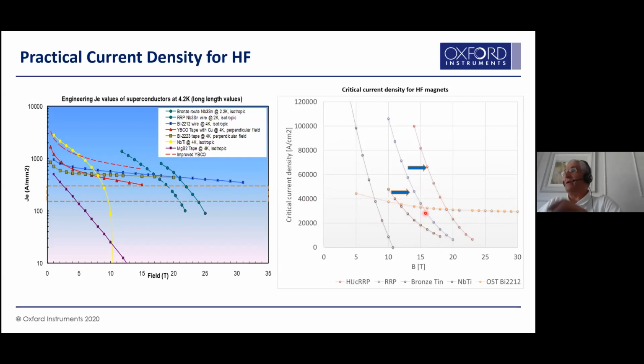And this has enabled a significant improvement in the performance of wire critical current density. And that's for a standard wire. You can see the significant improvement, almost 3-4 Tesla for the same current value. And then recently, OST has developed even higher JC performance, which means even higher current density for the same wire size. That has enabled us to start thinking about how to make these systems smaller in size, and we managed to reduce their size by almost 30-40%. However, this has come at a price of coil structure and energy management to manage these high performance materials in a high field environment.